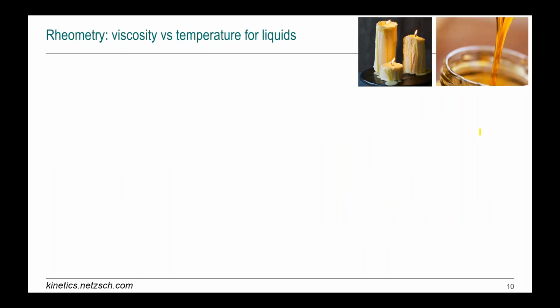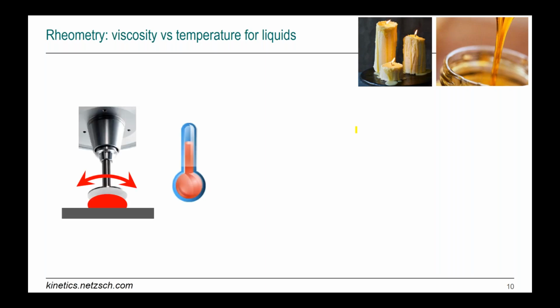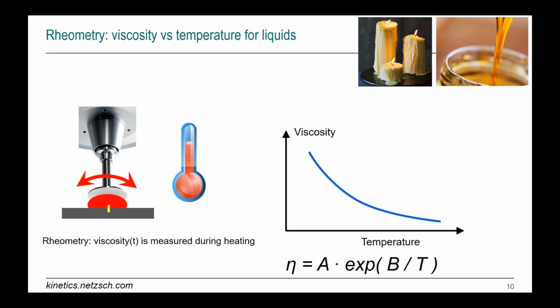Another technique is rheometry. Sometimes it's necessary to know how viscosity changes. We can measure this with a rheometer—for example a rotational rheometer. We put in our material and heat it. If nothing happens, no chemical reaction occurs inside the material, and we get a decreasing curve. At low temperature viscosity is high and the material is more solid; at high temperature the material is more liquid and viscosity is much lower.